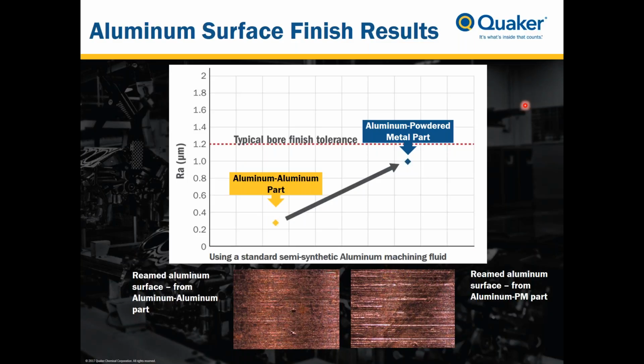Again, if you look at what most production facilities will set as a tolerance level for surface finish, it's typically about 1.2 to 1.3 micron Ra. So if we set that tolerance level here in our testing, you could see how the bimetal part, the powdered metal aluminum surface finish, is quickly approaching that tolerance level.